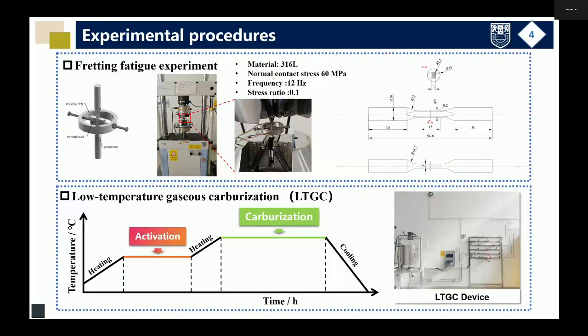This is the experimental procedure of my research. We carried out fretting fatigue tests using a bridge type fretting fatigue device. The normal contact stress was kept at 60 MPa. The loading frequency was 12 Hz, and the stress ratio was 0.1. Notably, the carburized samples were tested under the same conditions as the untreated ones.